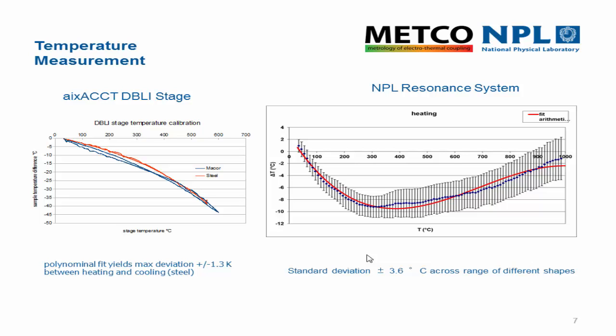We've mentioned temperature measurement, and this has been a common issue with all of the systems that we've been working with: simply putting a thermocouple in the vicinity of the sample doesn't give us a good temperature measurement. So for both the aixACCT system and for the NPL system, we've used some dummy samples and applied a correction based on those, which gets us to a reasonably tolerable measurement of the sample temperature.